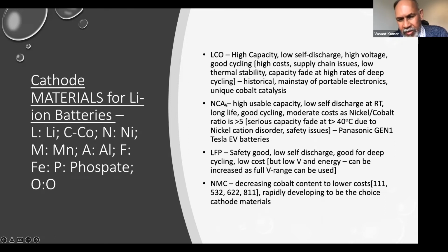And that's one of the reasons why Tesla chose NCA, for example. It's got a good capacity, and it's got good cycling. It's moderate cost because the cobalt amount is lower now. However, it has got one problem. At high temperature there is serious capacity fade. So therefore, it cannot be used in many parts of the world, especially in hot weather. And that happens because the nickel cation disorders. In other words, lithium can go into the nickel sites. So there are safety issues from that.